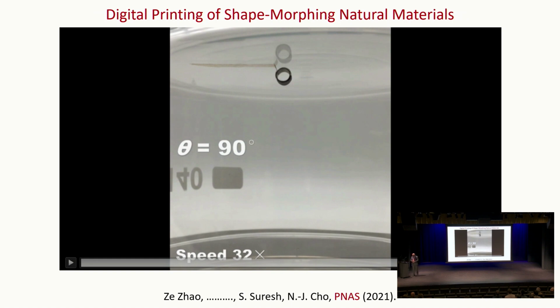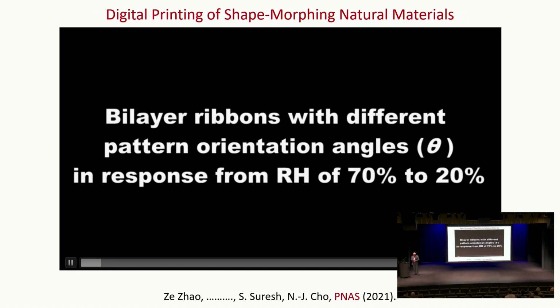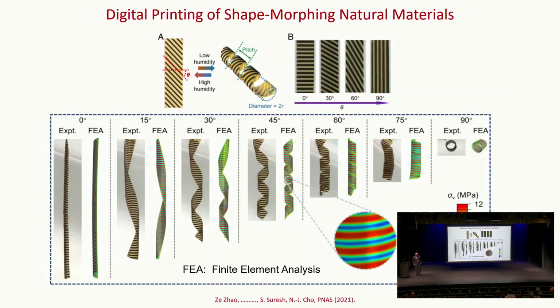So now, having demonstrated this, we can do a finite element analysis because it's a simple expansion problem of two layers. We know the orientation. So we do a finite element simulation for 0, 15, 30, 45, 60, 75, and 90 degree orientations for this paper. Experimentally, on the left, this is what you find, and finite element simulations will give you the prediction. You can predict it quite well. That means now you can design different shapes and different geometries of a very eco-friendly material, which is non-allergenic.